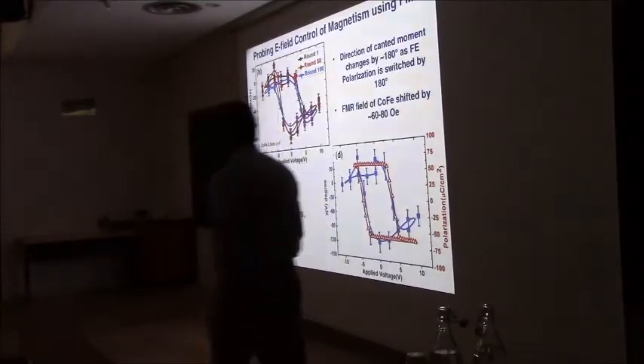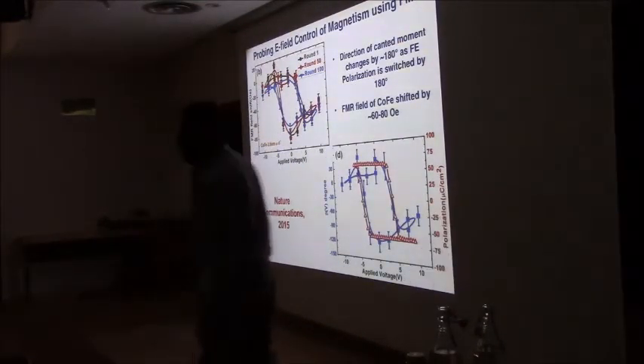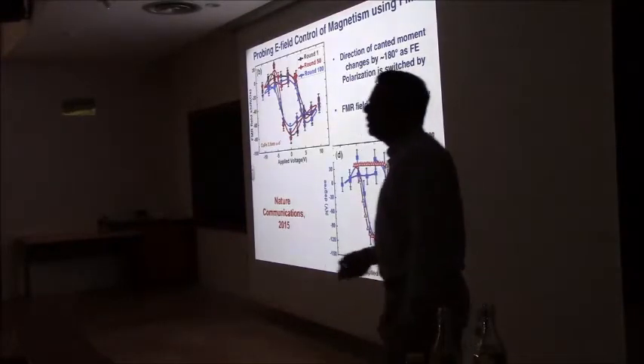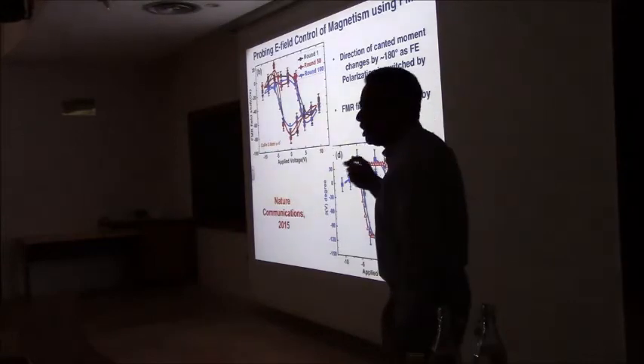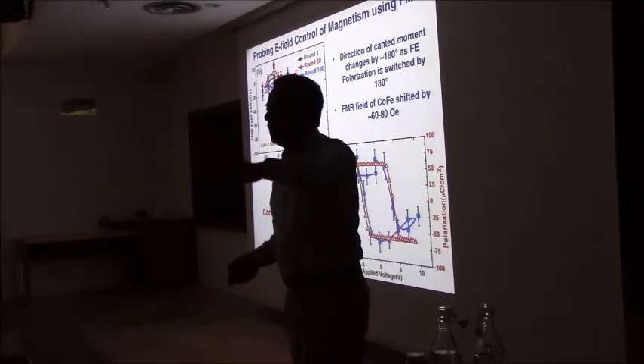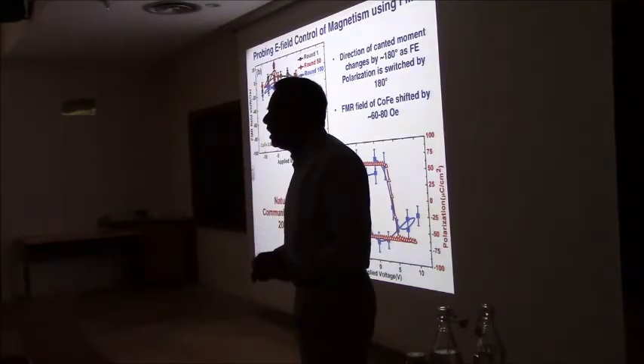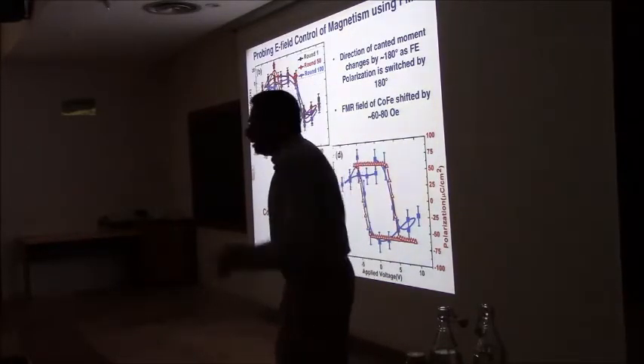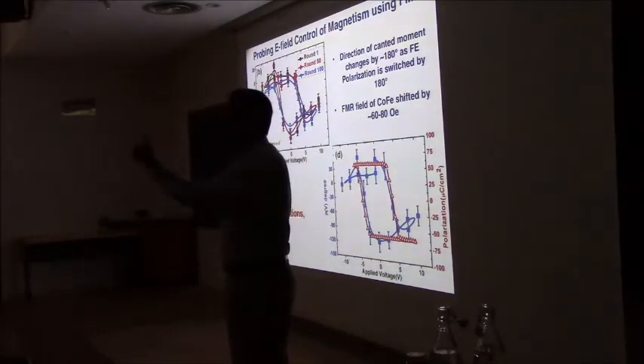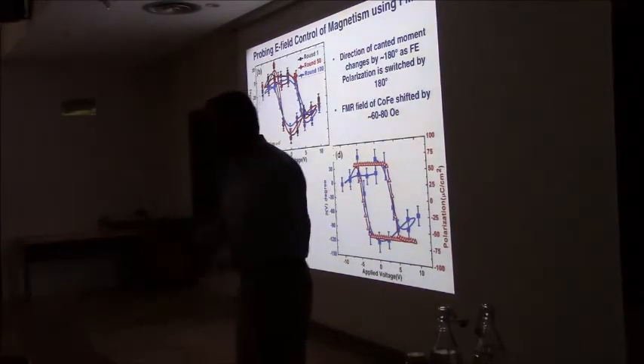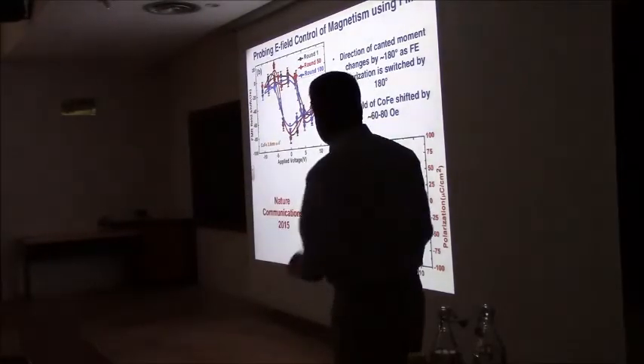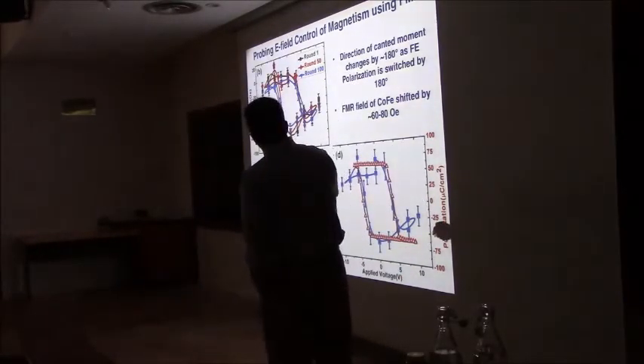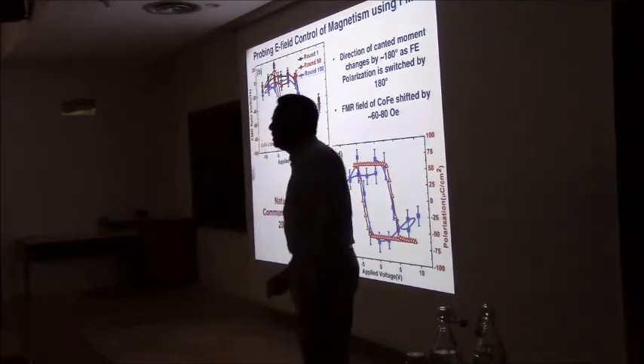The other way to measure it is by using ferromagnetic resonance. And this is a technique that, I don't know, did anybody talk about FMR? Yeah, so it's a separate talk by itself, but what we were doing is, you can set up ferromagnetic resonance in the ferromagnetic layer and ask the question, how does it change when I apply an electric field? And typically you will see changes in the position of the resonance peak. And you can manipulate that with magnetic fields. Of course, in our case, we're using electric fields.